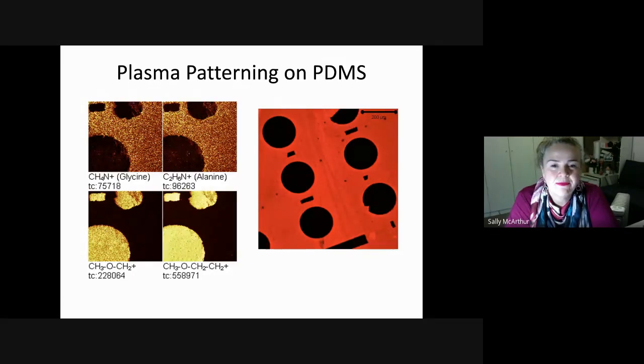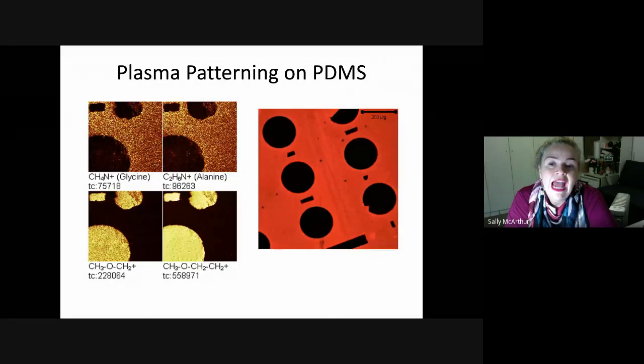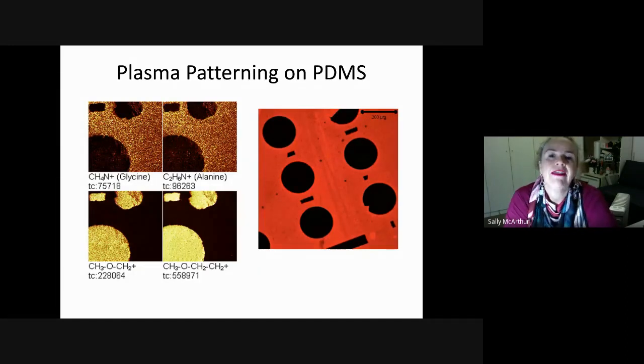And as surface scientists, it is verboten, do not bring these things into my lab. But the ability to actually put our plasma polymers onto these silicone elastomers was one of our big challenges. And so we've developed methods for doing that and for preventing that creep. So what we do in effect is use the plasma polymer layer to trap the low molecular weight monomers within the actual coating, so that we can then go on and pattern plasma polymers.